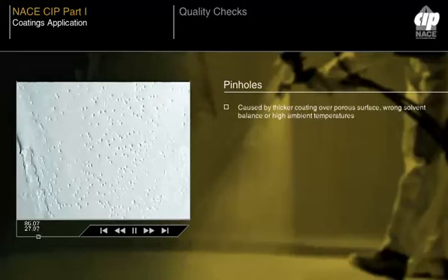High ambient temperatures may also lead to pinholing, as the film sets more rapidly. Fast-drying coatings such as vinyl or chlorinated rubber are most likely to suffer pinholing. The fast-drying surface does not allow the air entrained in the paint as a result of spraying, or the solvents, to escape. The name often given to this effect is gassing. The effect can often be seen after application of coatings as a form of bubbling, rather like the surface is boiling.